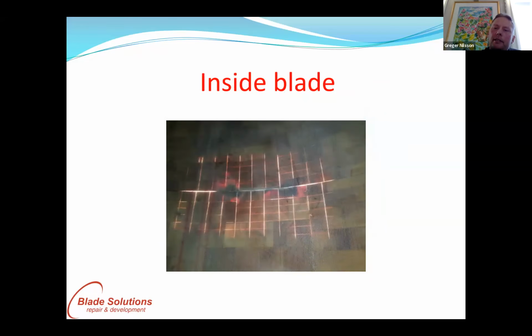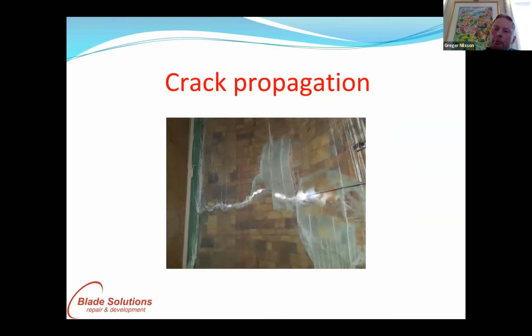And if you look, this is from the inside of the blade, you can see the same thing. You have some delamination around the crack here. If you don't repair, you can lose the blade. This is another blade that we inspected that wasn't repaired. So this blade had to be removed. You lost the whole blade from a similar start, I think.